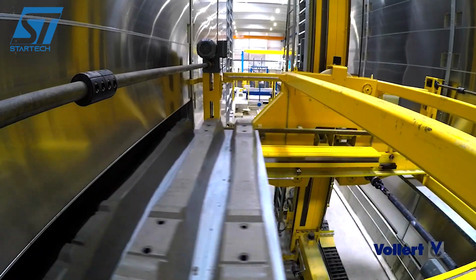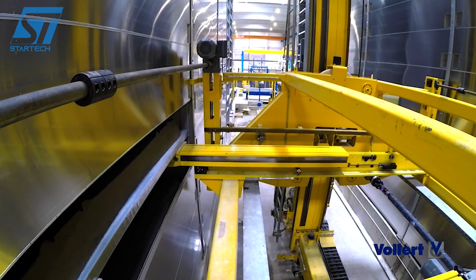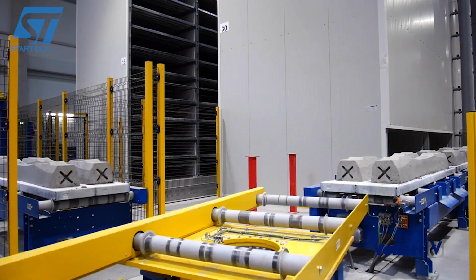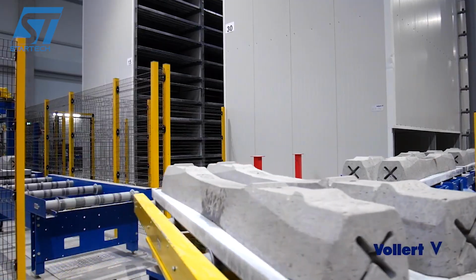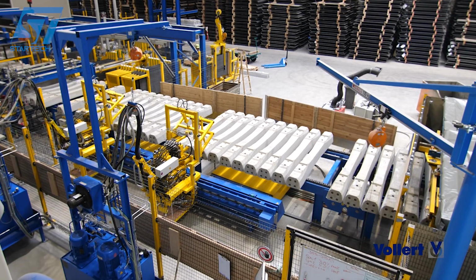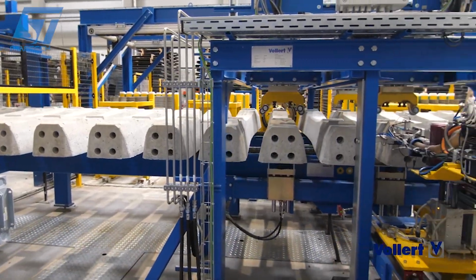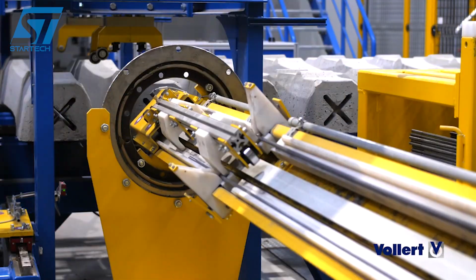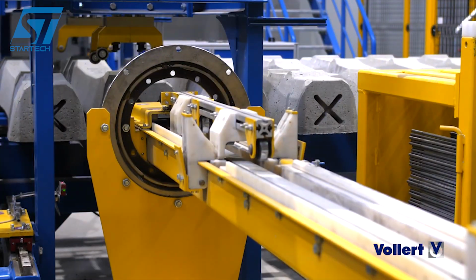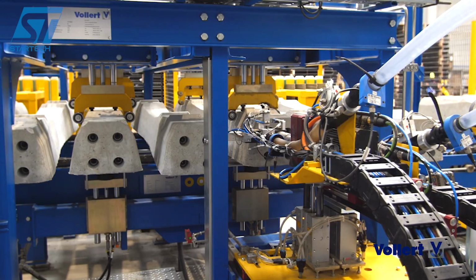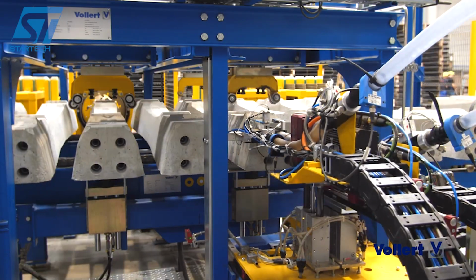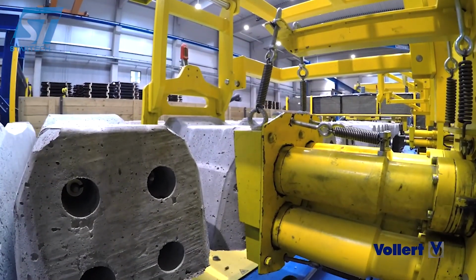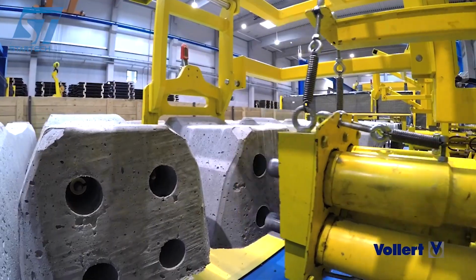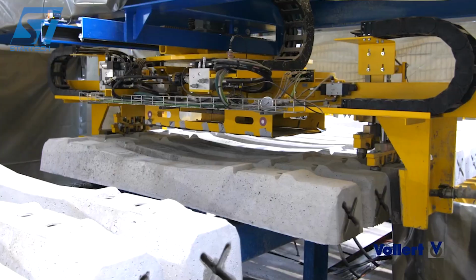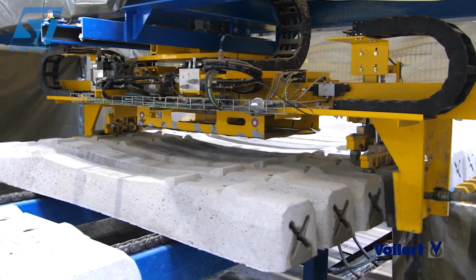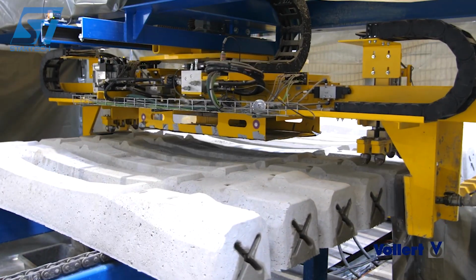Here's the critical part. The concrete needs to cure while those steel strands remain tensioned. The ties move through steam curing chambers where elevated temperature and humidity accelerate the curing process. What normally takes days happens in hours. Once the concrete achieves sufficient strength, typically around 7,000 psi, the pre-stressing force is released. As those strands try to contract back to their original length, they're locked in place by the hardened concrete, creating permanent compression throughout the tie.